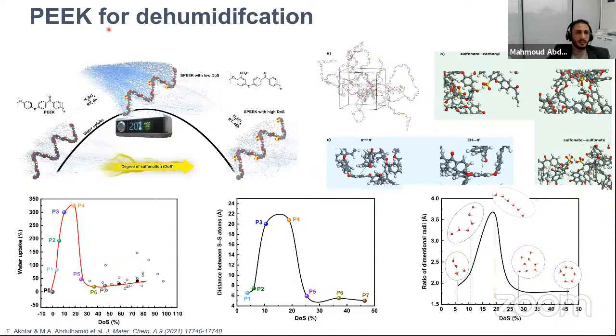Having mentioned the importance of PEEK, we thought, because there is no study about the degree of sulfonation, that, although this is not really related to porous polymers, I just want to go through it quickly. It is very important to know the effect of the degree of sulfonation on the performance of the material. It doesn't mean that if you have a higher degree of sulfonation, you have higher absorption or better performance. From experimental data we generated this curve, which shows that up to some point, when you increase the degree of sulfonation, you still get higher water uptake and higher performance. But after that, it starts to go down.